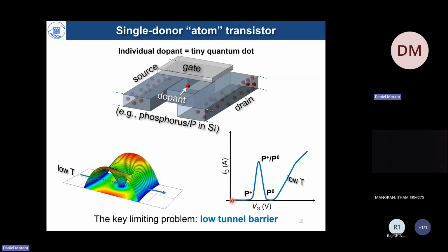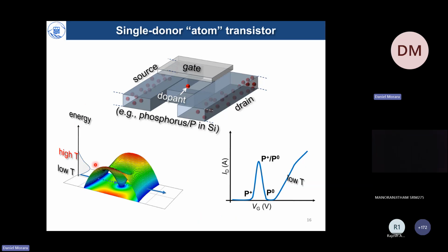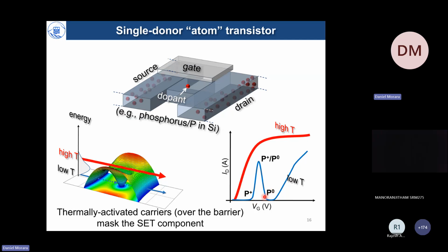Now, there is a single problem here. The barrier height could be at most 45 millielectron volts, because that's where the ground state is located in a normal phosphorus donor. So why is this a problem? If you increase the temperature, the Fermi-Dirac distribution broadens, and electrons from the tail of this distribution would be able to move above the barrier, create a high current, and hide the single electron tunneling current, which is this peak. So thermally activated carriers mask the single electron tunneling current component which we are looking for. So our group is chasing the practical operation of these devices at room temperature if possible, and we hold the world records in this kind of operation.